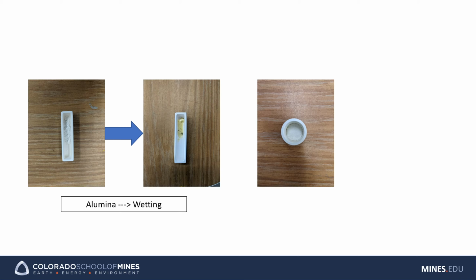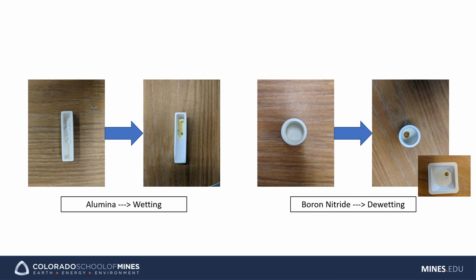So in this case, we chose a boron nitride crucible because it has different wetting properties relative to alumina. So ideally, this would mean that it wouldn't wet. Our powders would not have the same wetting effect in this new type of crucible. So we tried it out, and it turns out that assumption was correct. And by using these boron nitride crucibles, we were actually able to see dewetting that allows us to really easily pop the phosphors out of the actual boat itself, and we're now able to synthesize these high temperature phosphors,